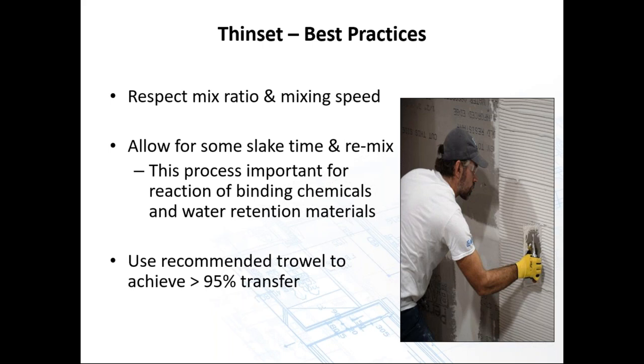Allow time for slaking and remixing, following the instructions put out in the manufacturer's recommendations on the proper way of mixing these mortars. It's important that the mortars have the right amount of time to bind, that the chemical reaction going on inside these mortars is taking place, that as you place the tile or the stone into the mortar onto the substrate, it's locking together and forming a complete bond so that the tile will stay there and we won't have a failure.